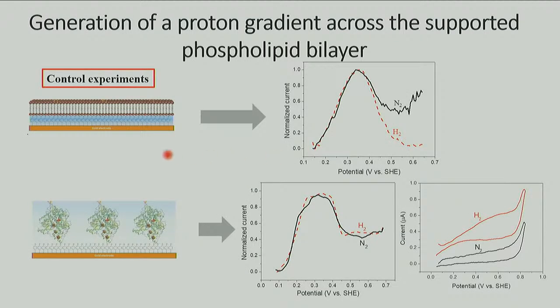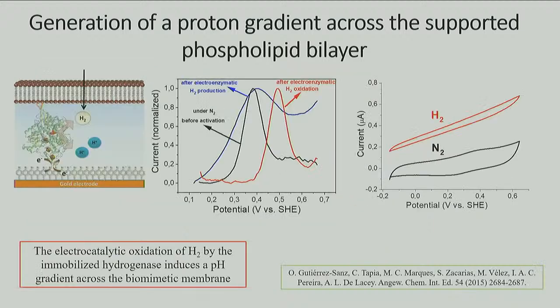Control experiments show that if we have only the membrane and we put hydrogen there, there is no way to oxidize this hydrogen, so the peak doesn't move. But if we put the enzyme and we don't cover it with this bilayer, and we put hydrogen, it's going to produce, but protons are going to the solution. So then there is no shifting. But if we cover it with the lipid bilayer, then we're going to make a higher proton concentration here, and we can see this shift. And when we put an ionophore, that is a molecule that is going to break this, it goes back.